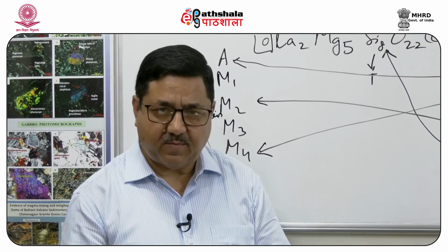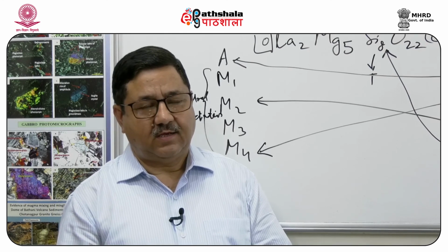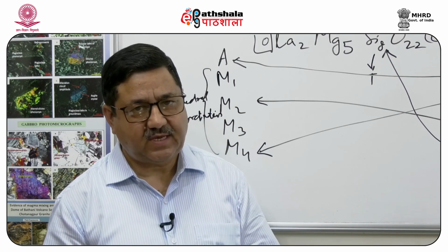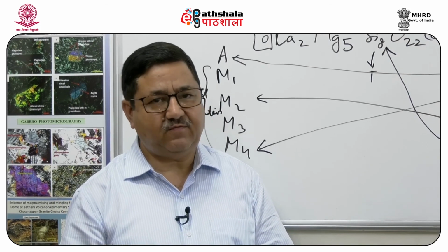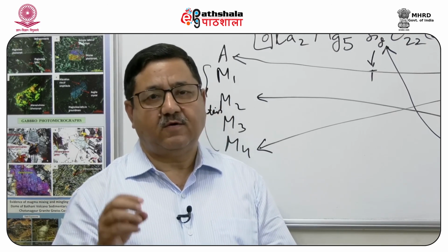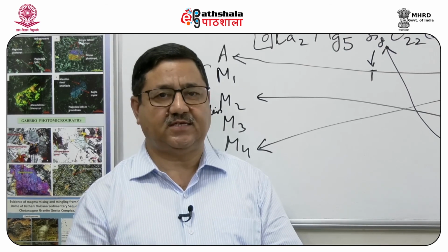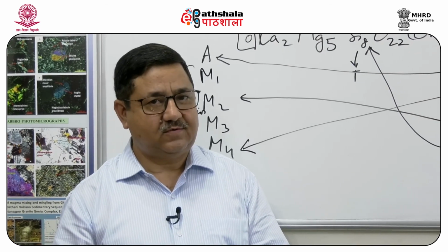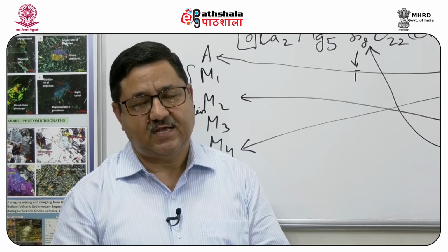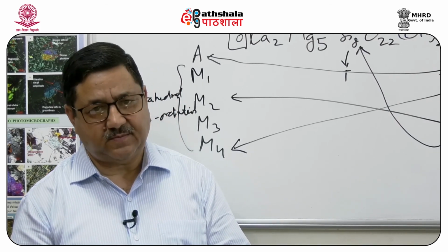Besides what we have learnt in Pauling's rules, there are a few more things to notice. For example, if we look at the uraninite structure where each uranium has 8 oxygen around it, and we look at the CaF2 structure where each calcium has 8 fluorine around it, there is a similarity of structure, though there is no relation of the constituent particles in the two cases. This kind of similar structure is known as isostructuralism or isostructure.